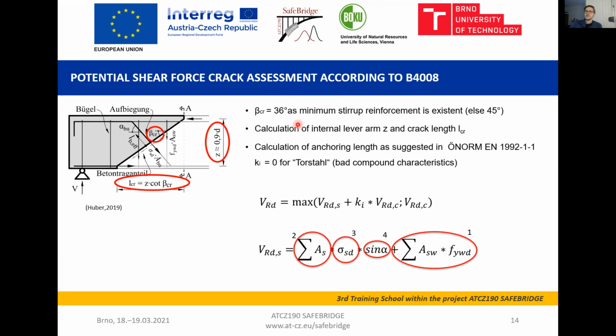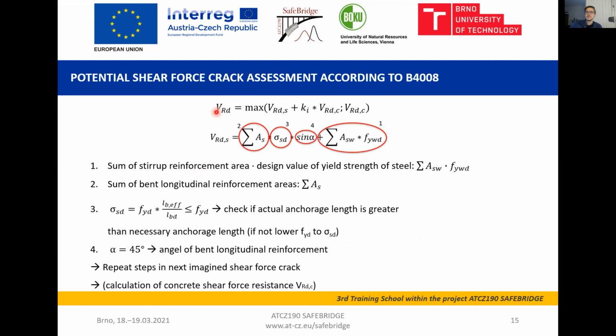The calculation first was the calculation of the internal lever arm and the calculation of the critical crack length. The shear crack is calculated with the capacity of the steel and the capacity of the concrete without reinforcement, but we had to assume ki, a factor for the steel you use, is 0 because the steel is from 1957 and has a bad bond. This potential shear crack assessment takes time to assess. It's not as easily applicable as the Eurocode, so it takes some steps.